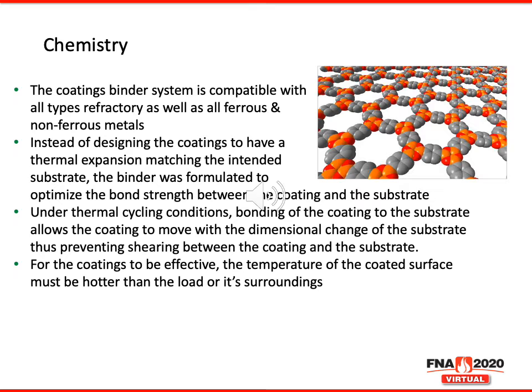The coatings were designed to be compatible with all types of refractory, as well as all ferrous and non-ferrous metals. A unique property of these coatings is that they will move with the dimensional change of the substrate, thus preventing shearing between the coating and the substrate. In order to do this, the binder in the coatings was formulated to optimize the bond strength between the coating and the particular substrate. And once again, for the coatings to be effective, the temperature of the coated surface must be hotter than the load or its surroundings.